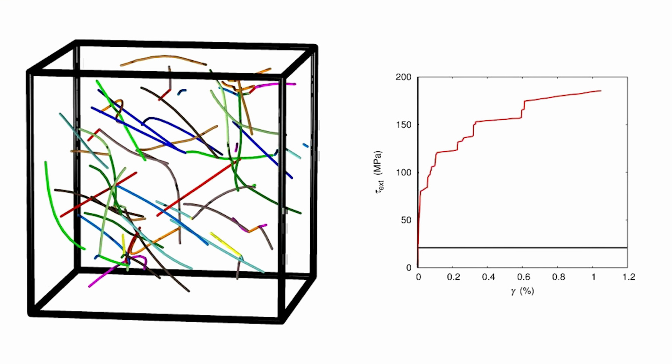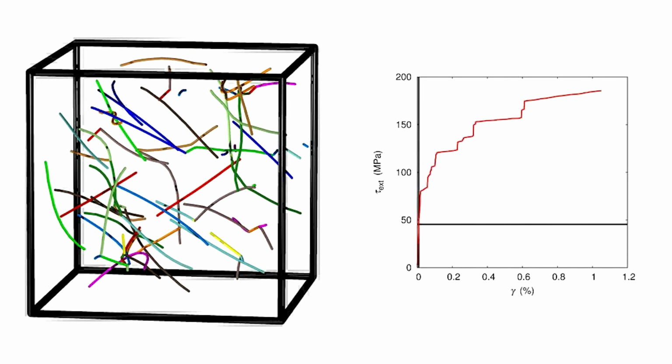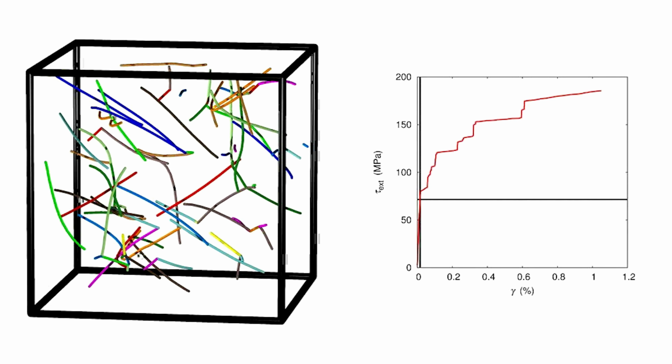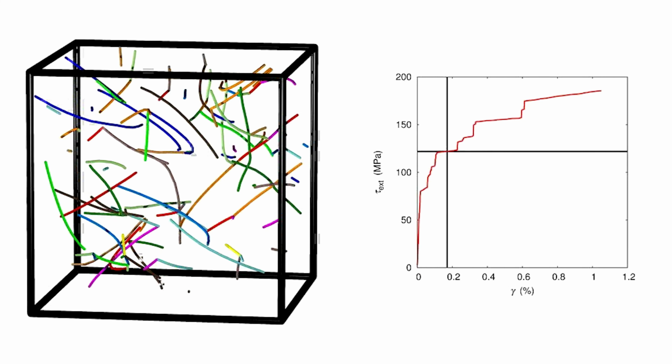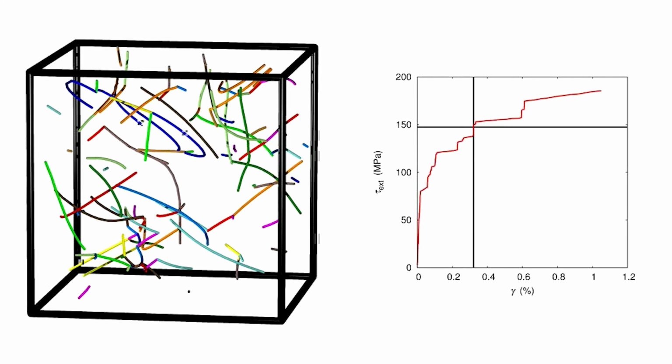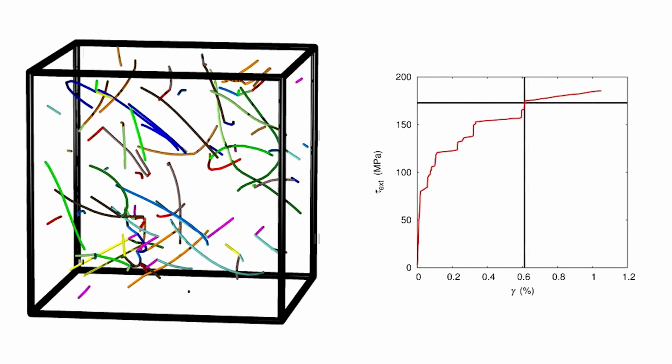During these intermittent bursts, dislocations, shown here as coloured lines, locally disentangle, move quickly for a short period, and form novel metastable substructures at the end of an event.